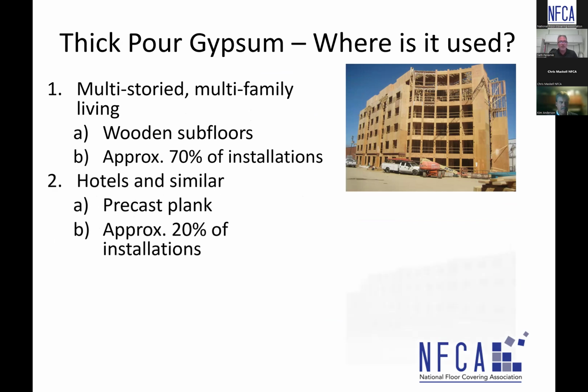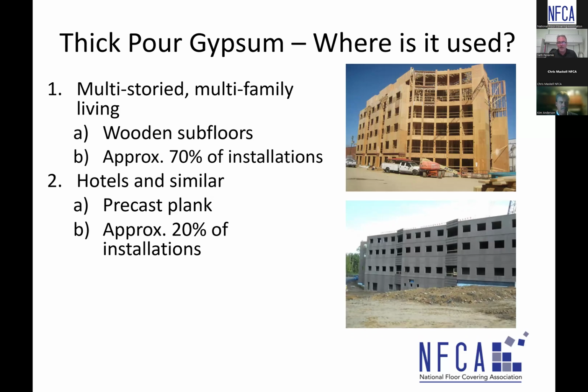Another application that you typically see would be precast plank. These planks are made at a manufacturing plant. They're called hollow core plank because they have hollow cores in the middle, but they're trucked to the job, installed, and craned into place. Each plank, after it's dropped into place, typically has some sort of camber problem where one plank doesn't meet up perfectly with the other, and that difference they call camber. It requires some sort of self-leveling to be poured over the whole floor at some greater depth to make a flat surface, and thick pour gypsum is one of the products that gets used. Hotel applications use these hollow core planks, as do other similar applications. That's probably about 20% of the thick pour gypsum that gets installed in North America.